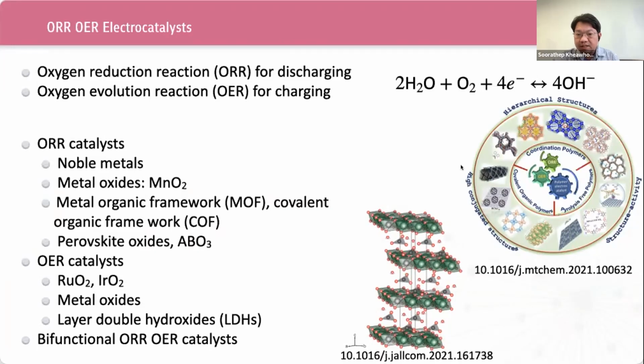For OER, ruthenium oxide and iridium oxide are both excellent catalysts. However, again, they are both too expensive. Metal oxides show acceptable performance. Our group is working on layered double hydroxides. Layered double hydroxides are excellent OER catalysts, and they can be fabricated as a self-supported structure, which exhibits excellent stability. Our recent article can be referred here. It's on layered double hydroxide.